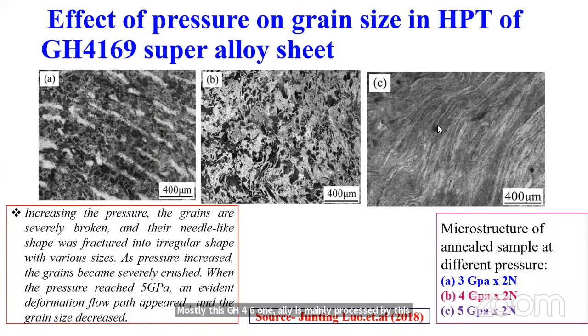You can see these 3 different microstructures. The 3 different microstructures are produced by pressing the samples at different pressures and different number of cycles. You can see the microstructure of the annealed sample at different pressures. The first microstructure is with 3 gigapascal pressure applied with 2 passes. You can see the grains are severely broken with 3 gigapascal and 2 passes. You can see the shape of the fracture. The needle-like shape of the grain was fractured into an irregular shape with various sizes. You can see different sizes of the grains.